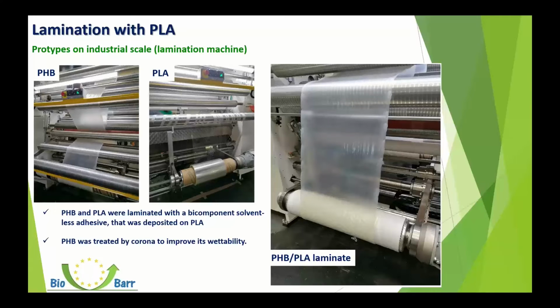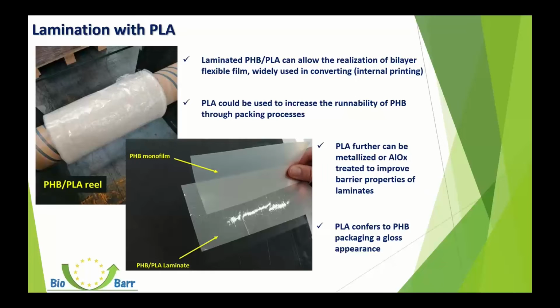According to this configuration, we decided to perform the realization on the industrial scale of a prototype of a real PHB PLA laminate, in which PHB was chosen as a secondary layer and PLA was chosen as a primary layer. The lamination was performed using a bicomponent solventless adhesive that was deposited on the primary layer, that in this case was the PLA. We decided to use a solventless adhesive in order not to stress further the PHB material with the temperature and with the use of a solvent. The PHB before the lamination was treated by corona treatment in order to improve its wettability. So we realized the PHB PLA laminated reel.